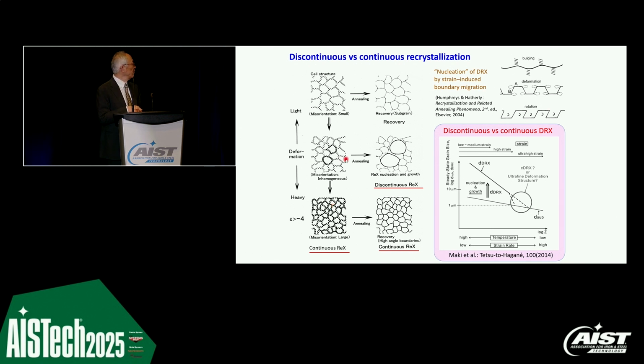And there are two different curves for the grain size versus Z parameter. This is the recrystallized grain size, and this is the subgrain size. But applying further higher strains, we have really a mixed region between the two lines intersected. Now we are having the transition from the discontinuous recrystallization to the continuous recrystallization.